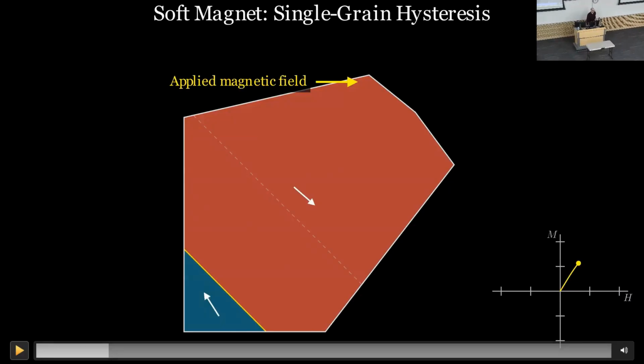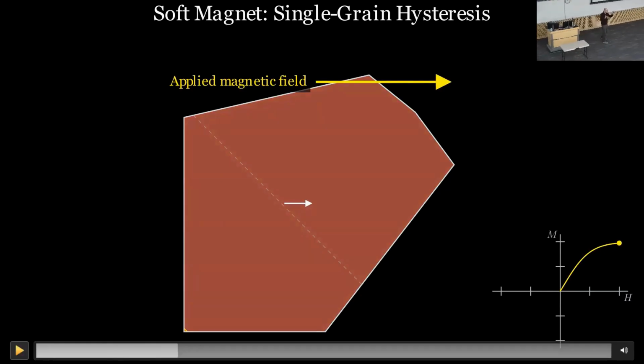What we will typically do is find out how much total magnetization we can get out of a sample. So we will apply an external field until it starts to plateau. If you look at the plot at the bottom, you'll see it starts to plateau. That tells us that we've basically made the whole magnet into one domain. Right? You see there's red completely dominates here.